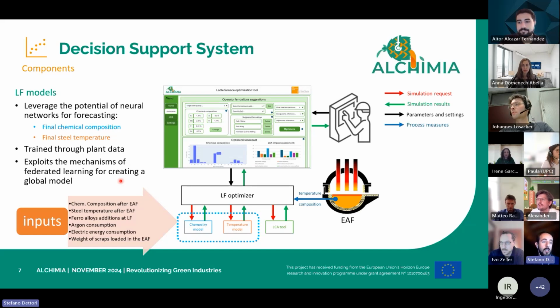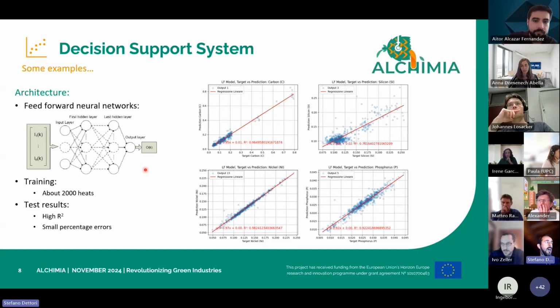These models exploit, obviously, a set of inputs that are, for example, the chemical composition during the tapping in the EAF, so the chemical composition of the steel, the steel temperature, ferroalloys addition, the argon consumption for stirring, the electrical energy consumption, and also the weight of the scraps loaded in the electrical furnace. And this is an example of how, in a test set, these models work. These models exploit a quite simple architecture based on feed-forward neural networks, trained with about 2,000 heats, but thanks to the federated learning approach, this model will be enhanced through a lot of data from all the plants participating in the project that exploit a ladle furnace.